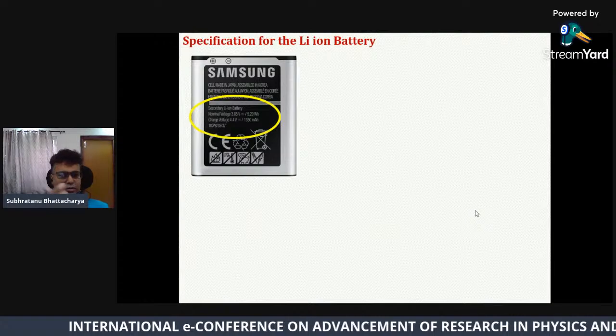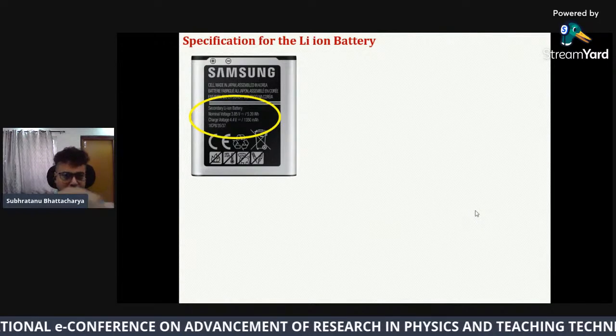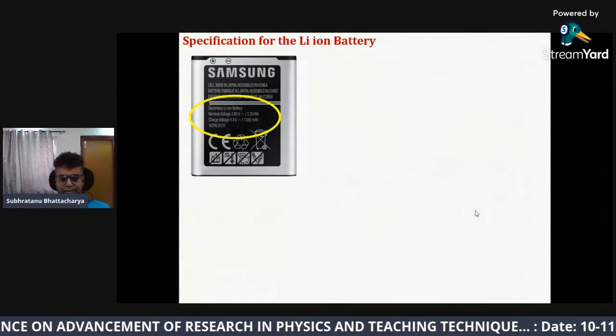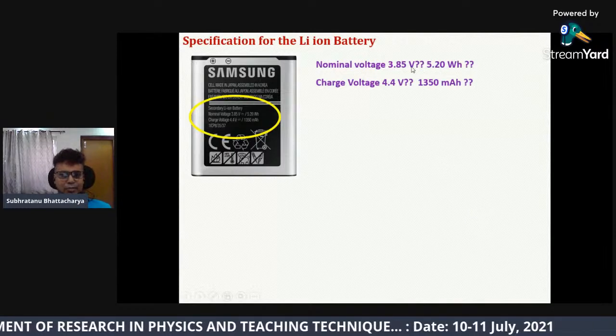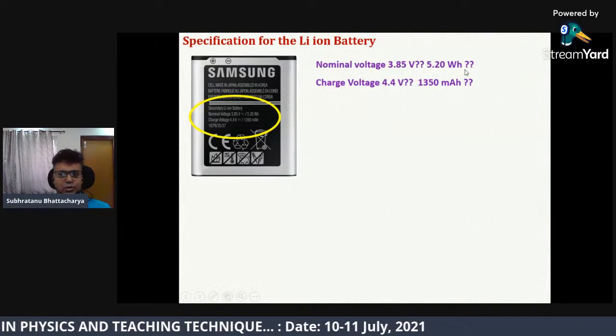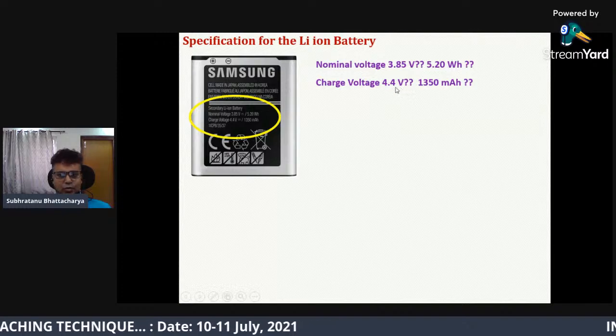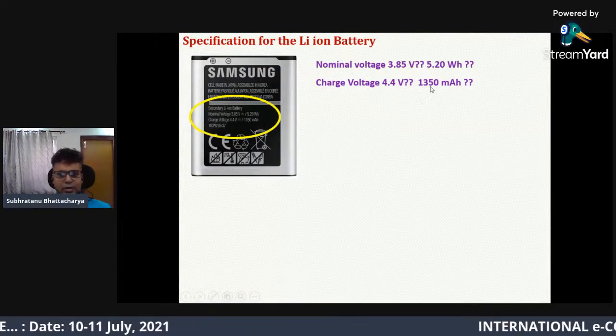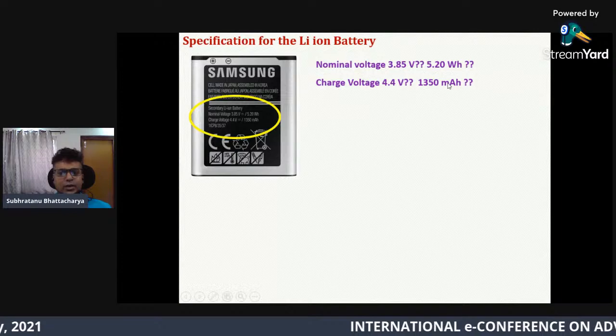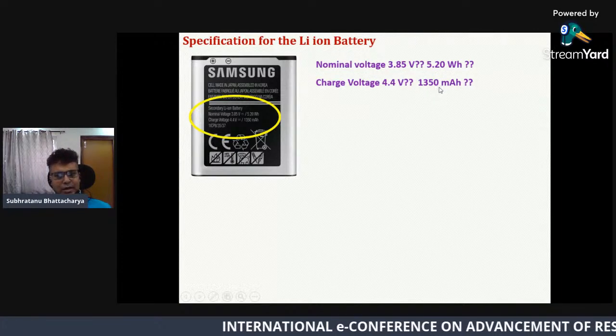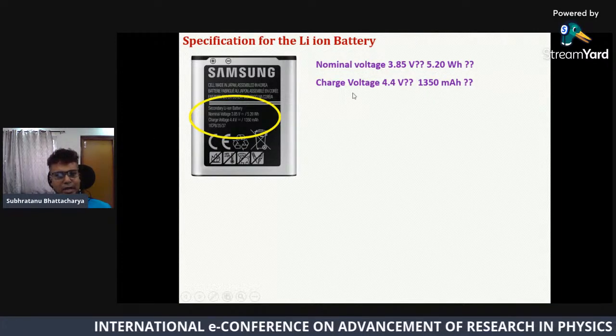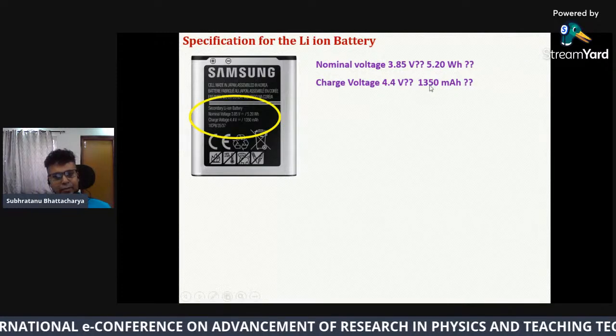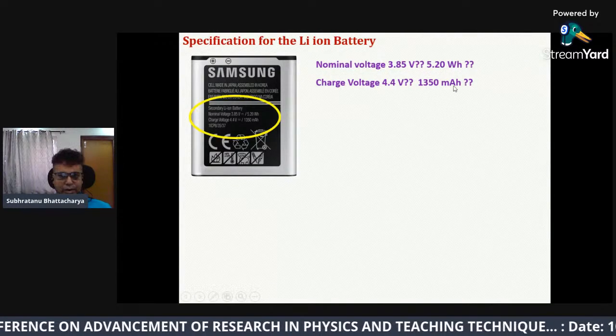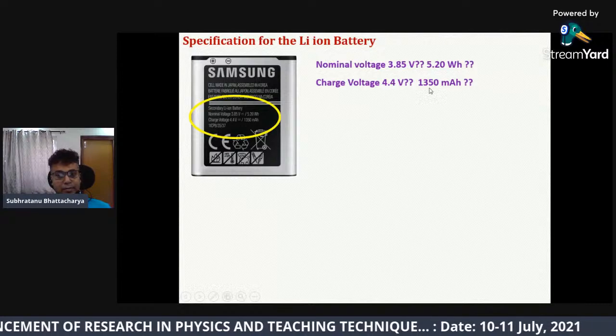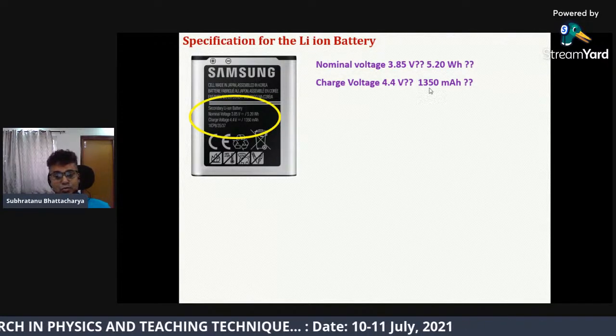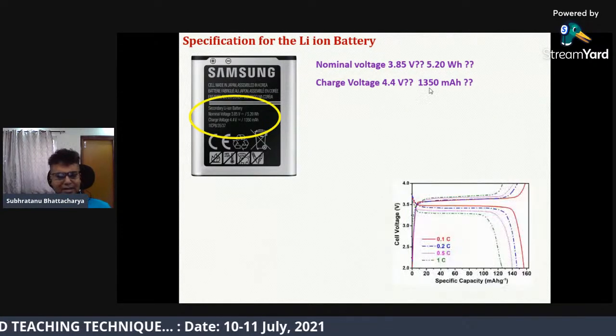Now I am coming to these terms which are actually written on a battery, like nominal voltage 3.85 volt, 5.20 watt-hour, charge discharge voltage 4.4 volt, capacity 1350 mAh. You can understand this now: what is 1350 mAh? This is the total active material multiplied with the theoretical capacity, and you get 1350 mAh. Now if it is a 5000 mAh battery, it means you have to use more active materials for that.